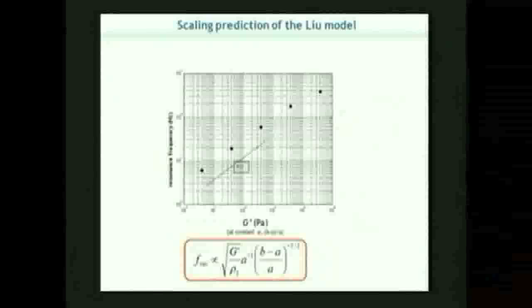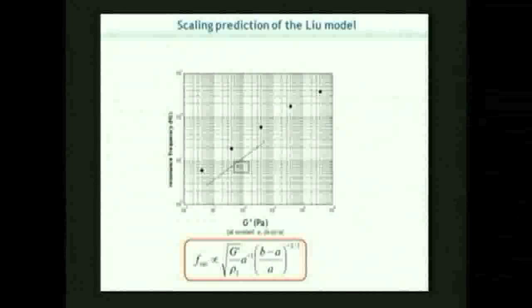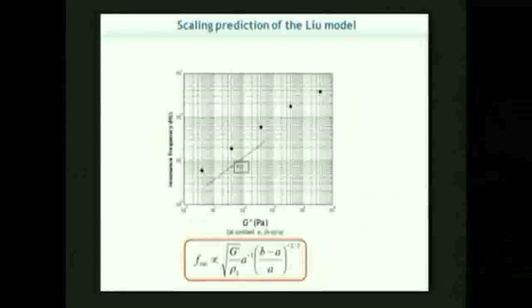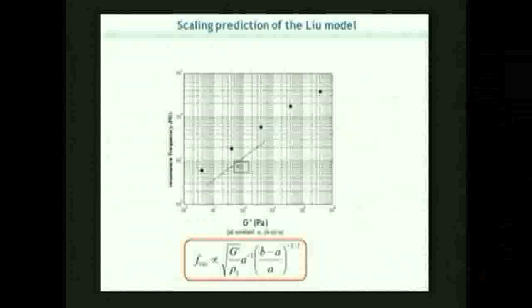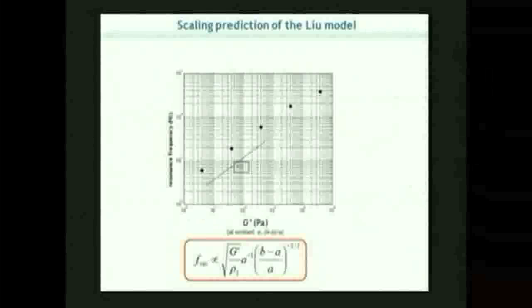Here you have a plot of the resonance frequency as a function of the value of the elastic modulus of the shell. Okay, so this resonance frequency is a function of the dimension of the object and also of the physical properties of the materials that constitute the core and the shell of the sample.